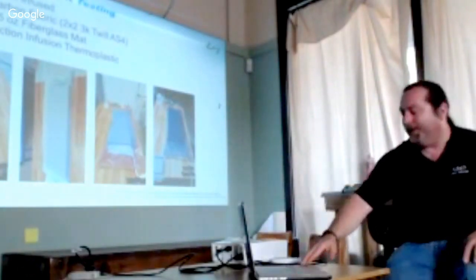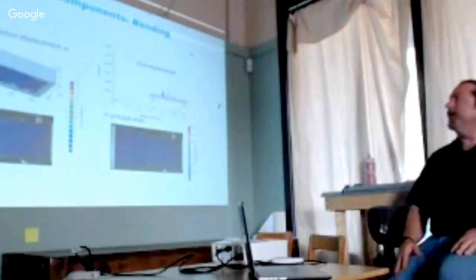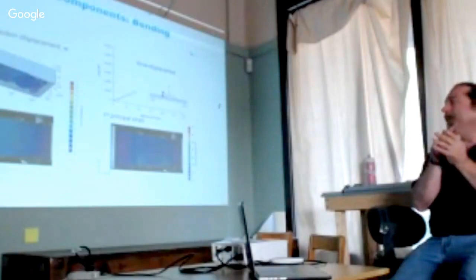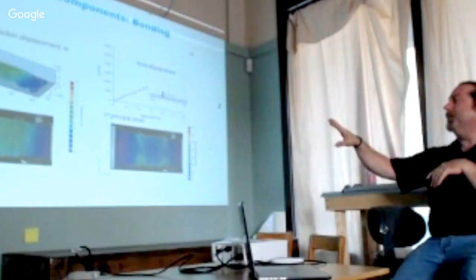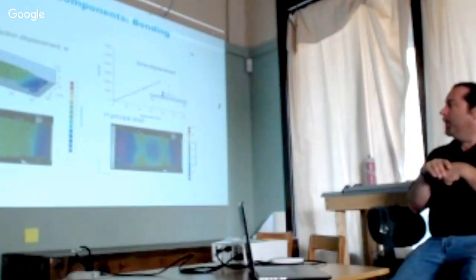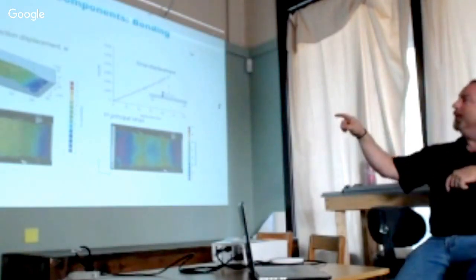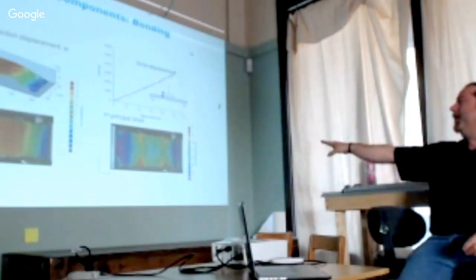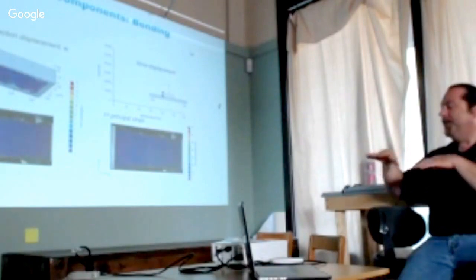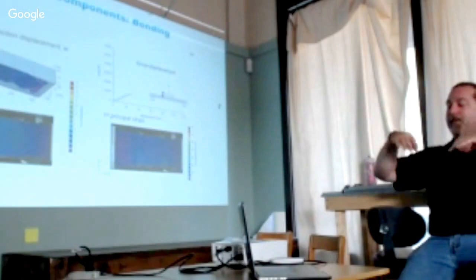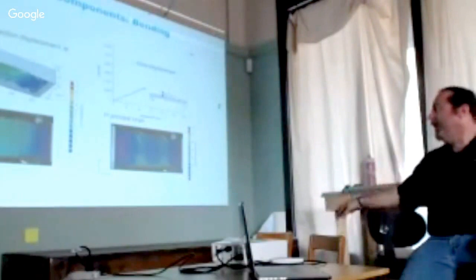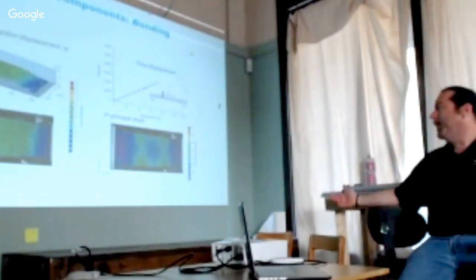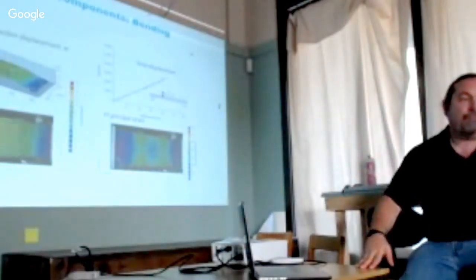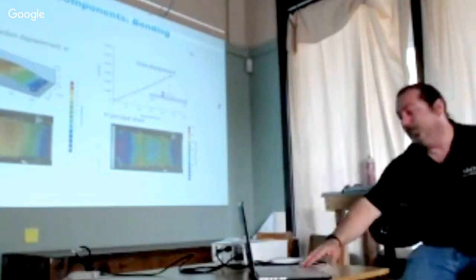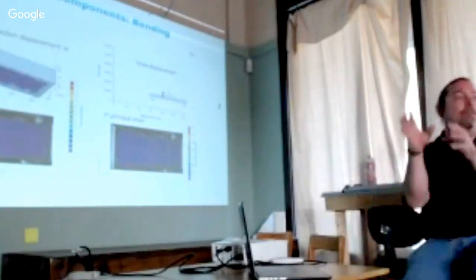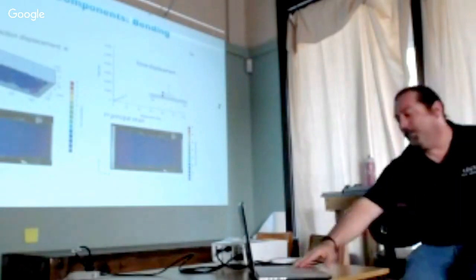This just shows the overwrap process again, and this is what that data looks like. This is the chevron infill box in 4-point loading. This is the full field strain measurement: the Z direction displacement on the left, and the first principal strain, the surface strains, on the right. You can see the effect of that infill underneath the surface resolving as a difference in surface strain. We've just started to do finite element analysis and getting some correlation with this data. We collected this data on all 102 tests, and for our phase 1, we were going to do the testing, and then phase 2 is the simulation effort.